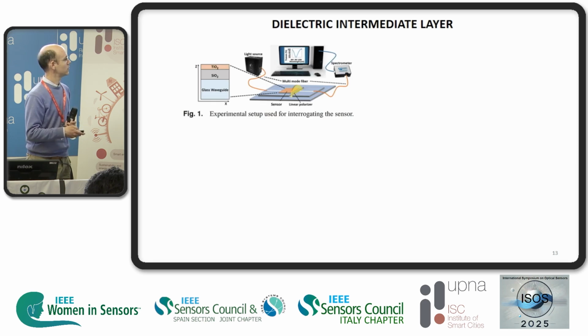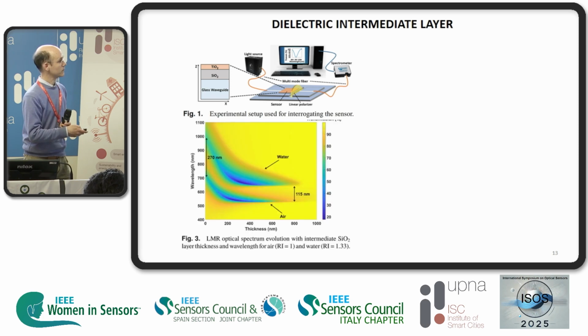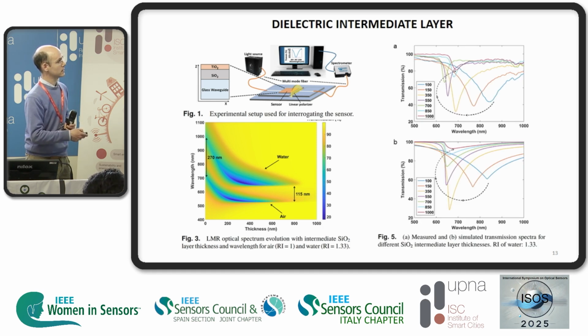This was a work published a few years ago by Dairon Armas. He used this setup: a glass waveguide deposited with titanium dioxide, and the intermediate layer is silica. By simulations, we observe as a function of the thickness of the silica layer that the resonance shifts in wavelength, and there are some thicknesses where the resonances are more visible, here and here. So in one case for TE and TM, around 300 nanometers, in the other 200. The best thing here is that we improve the visibility of the resonances, and this was confirmed experimentally: the resonance is shifted to shorter wavelengths, there is a maximum of visibility, and later it fades, similarly to the simulations.